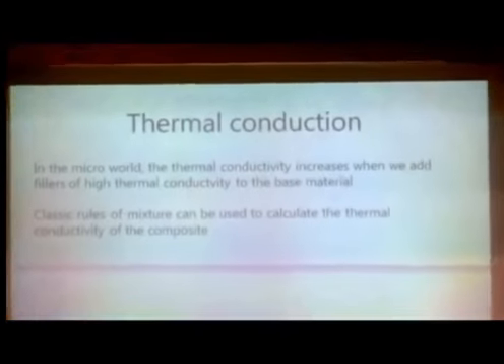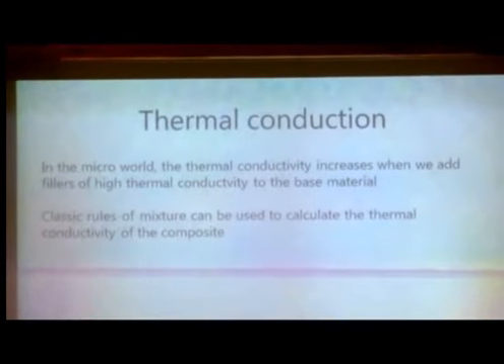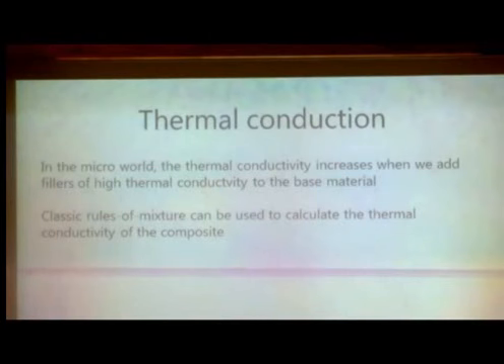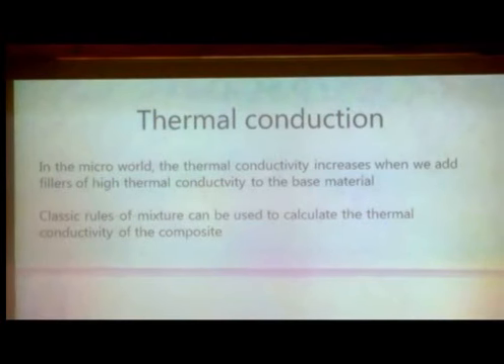A totally different example here. We're still on the nanoscale, very small. Thermal conduction, as I mentioned, is becoming more and more important in our field. And in the micro world, the thermal conductivity increases when we add fillers of high thermal conductivity. Epoxy resin is always filled, 50–60% of silica, for instance, to make it cheaper, of course, to tailor the mechanical properties, the thermal properties, and so on.